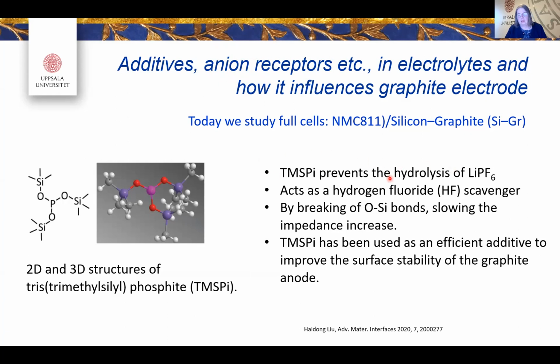And this anion receptor is to take care of the LiPF6 anion and prevent the hydrolysis of that and the formation of HF. You can call it then an HF scavenger, this tris(trimethylsilyl) phosphite additive. And it's breaking these oxygen silicon bonds, which is slowing down an impedance increase in the battery as a function of the hydrogen fluoride formation. If we can prevent that, we also prevent an impedance increase.